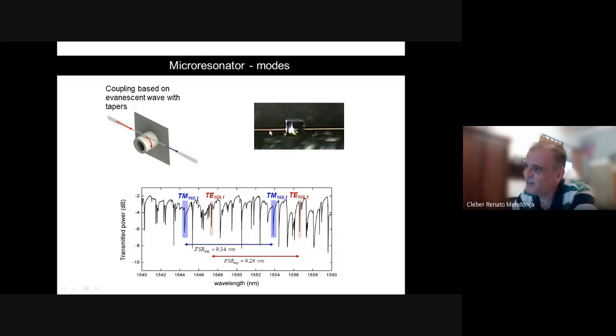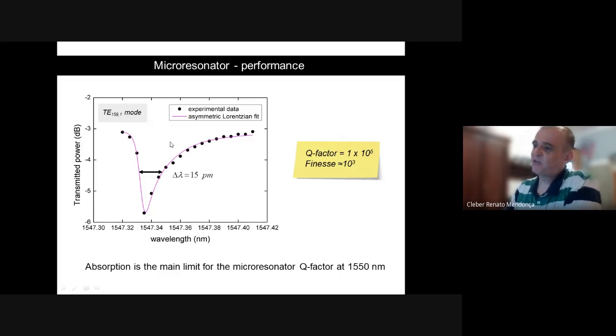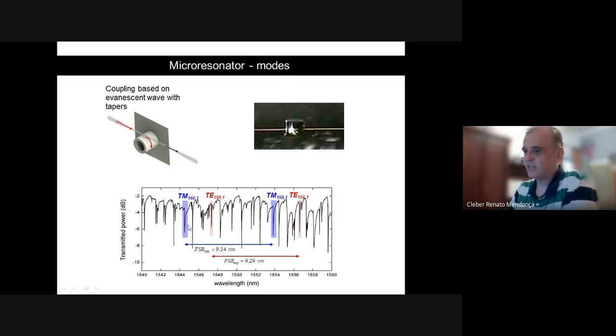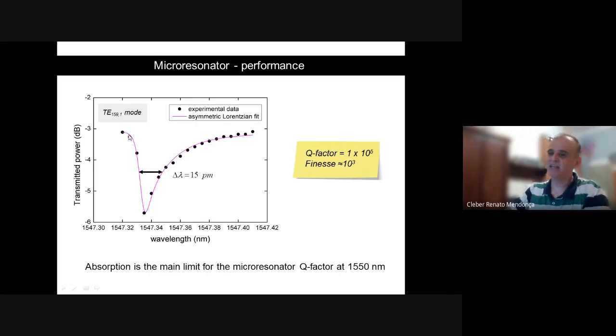As you see here, the resonator and the optical fiber in the back, and here is the resonance spectrum of the microresonator. As you can see, we get different resonances depending on the modes. The free spectral range is the one we are expecting, so everything works fine here. By taking one of these resonances, we can analyze it and estimate the quality factor, which is 10 to the 5th, which is actually the limit for polymeric resonators. So there is not much way to increase the quality factor, but it's a very competitive quality factor.